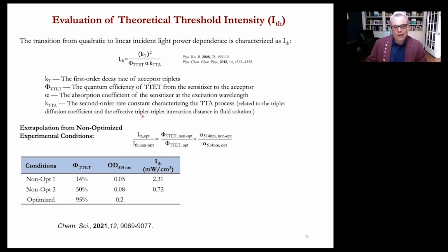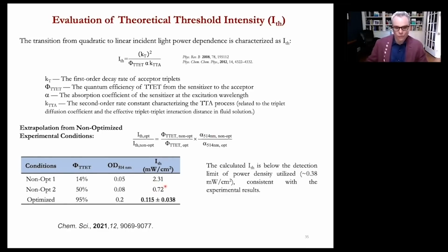So if you think about it, we can do some ratiometric concepts here of really changing this and then knowing what the absorption coefficient is at 514 nanometers. You can see here under the non-optimized conditions, we have those I values. So when it's optimized, we believe the I value should be about 0.1 milliwatt per square centimeter. So that's a very rough approximation. I'm not going to pretend that that's the best way to do this quantitatively, but it is a good qualitative measure of where it should be. This is why we couldn't experimentally observe it, because we can't excite at that low a power and actually measure the optical power properly. So it shows you this thing is absolutely amazing.